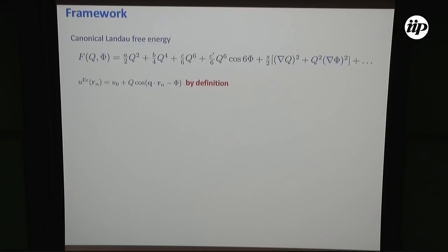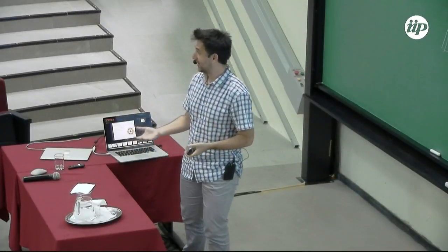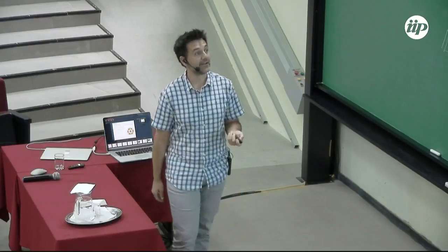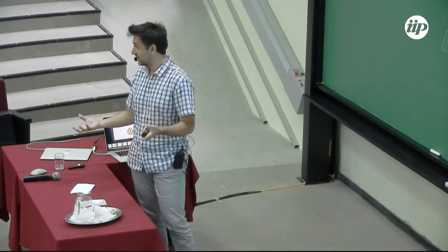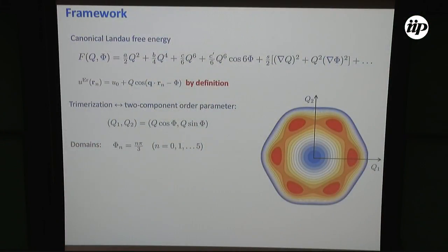This is very important to keep, because this is related to the hexagonal symmetry of our system, and because of this, we obtain 6 trimerization domains. So this term is essential for us. As a result of this term, the energy landscape looks like this. We find 6 different minima. Each of these minima corresponds to one domain. And for example, if the C prime parameter is positive, we find discrete values of the phase of the order parameter according to these 6 minima that we have here.